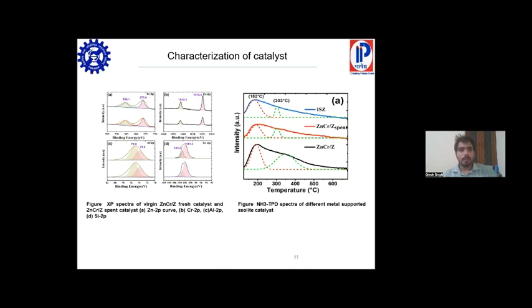Then come to aluminum 2p, which shows 2p1/2 at 76.8, and the other spin component at 75.6, which corresponds to 2p3/2, which can indicate alumina in +3 oxidation state. Then come to silica, showing +4 oxidation state.